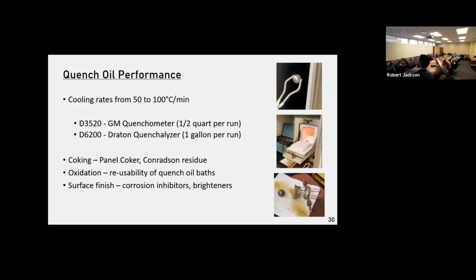You almost use the magnetism of this ball as a thermocouple or a probe. So once it reaches 600 degrees Celsius or below the Curie point, it swings over and hits a magnet and makes a clink, and then you can measure your temperature or how quickly it went from 850 Celsius to 600. And that gives you a basic cooling rate. You can stack that up against how fast or slow you want to quench your workpiece.